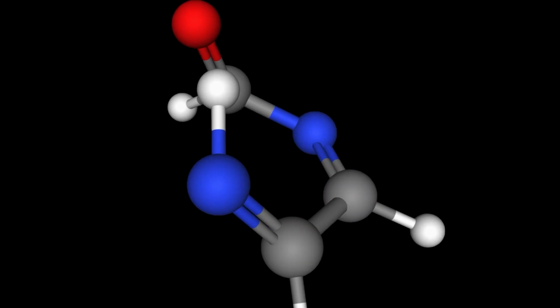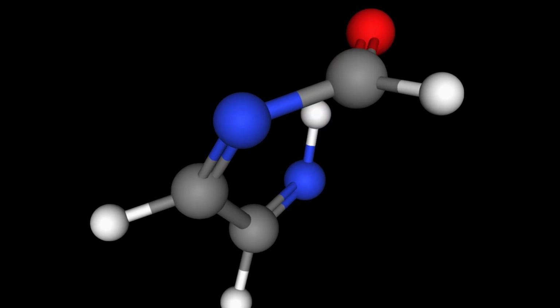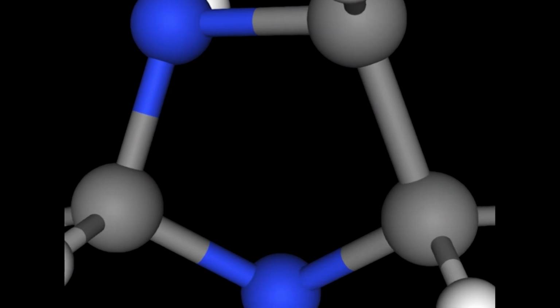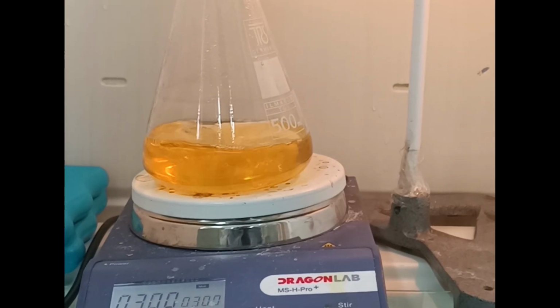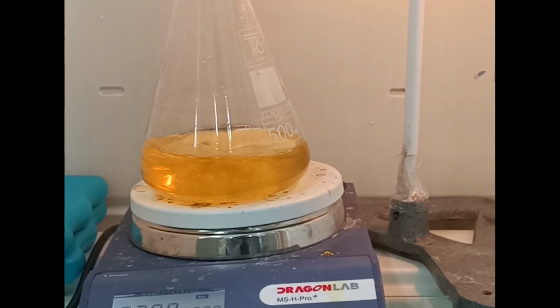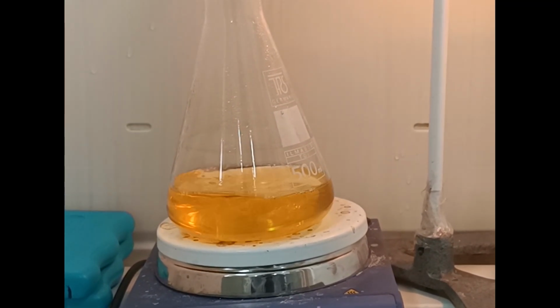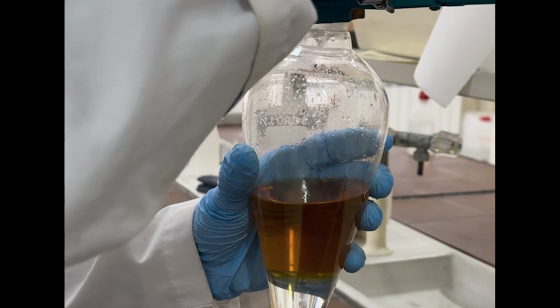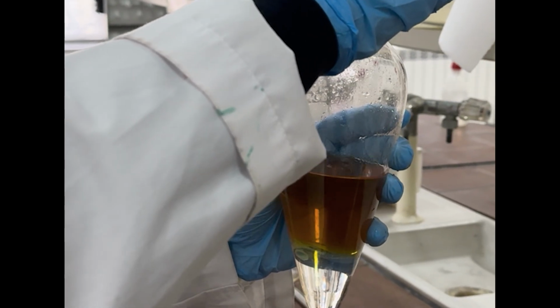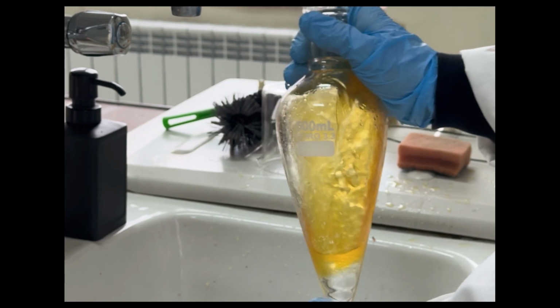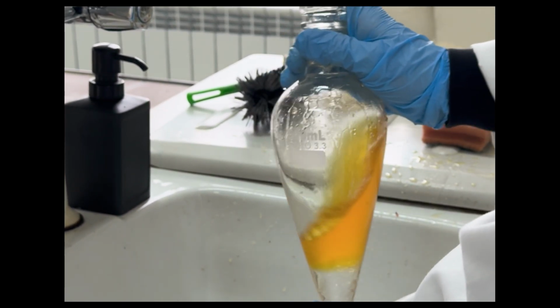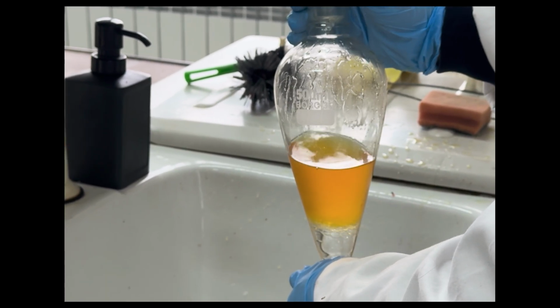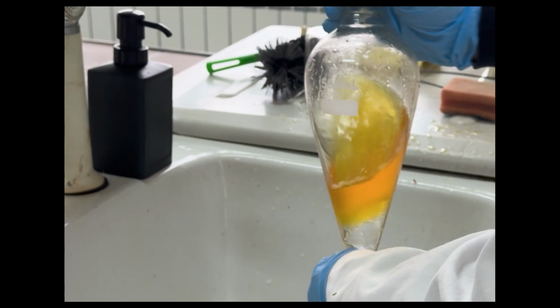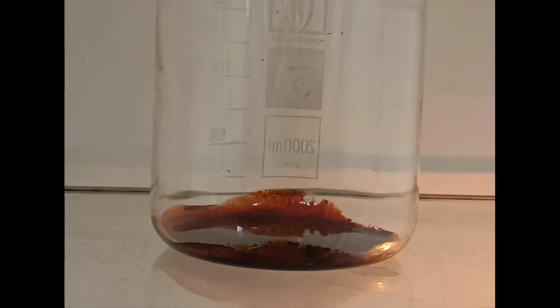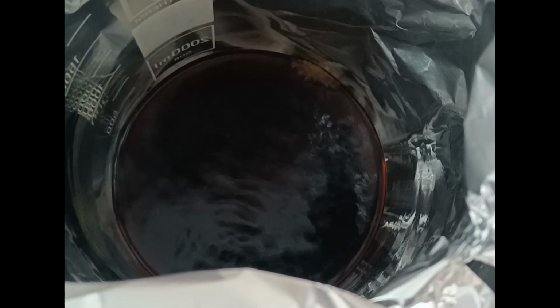Once the diimine forms, it reacts with the formaldehyde to generate an amino alcohol intermediate. That intermediate cyclizes, forming a dihydroimidazole ring, and then dehydration plus tautomerization aromatizes the system into imidazole. After slowly adding ammonia and letting the reaction stir overnight, first in a cold environment, then at room temperature, the solution darkens slightly. Purification should have mostly been acid-base chemistry, as acidifying the mixture with hydrochloric acid would have turned the imidazole into the water-soluble imidazolium salt, and any organic impurities would have been extracted away with dichloromethane, and then basification with sodium hydroxide would have turned everything back to normal. Luckily, the solubilities of the two are very different, and imidazole can dissolve in cold ethanol, whereas the salt does not. So water is evaporated, and then ethanol is used to extract only the pure imidazole.